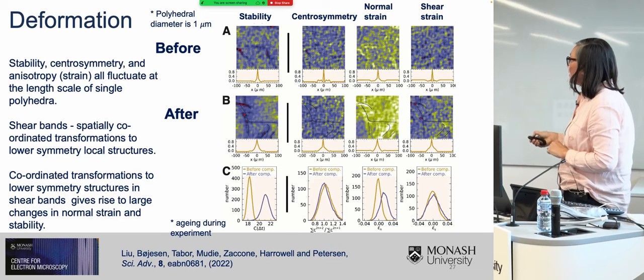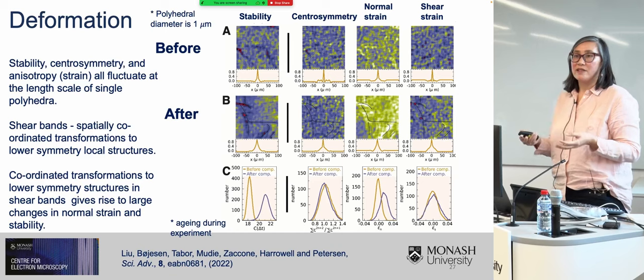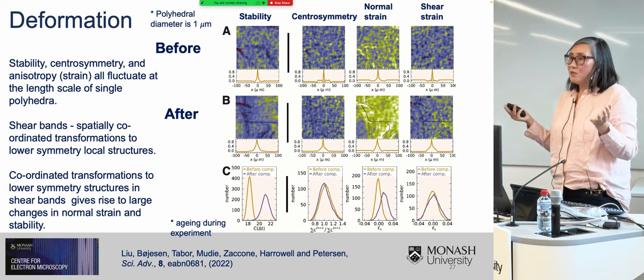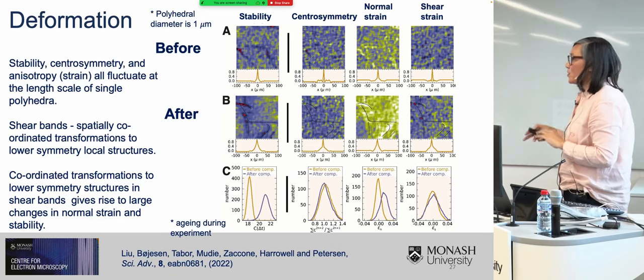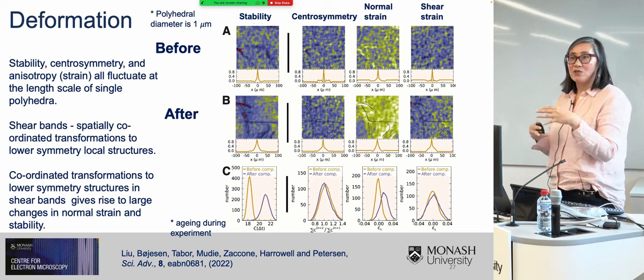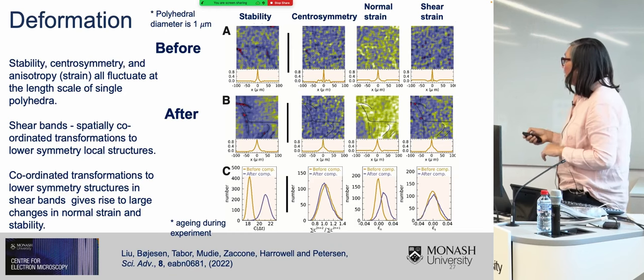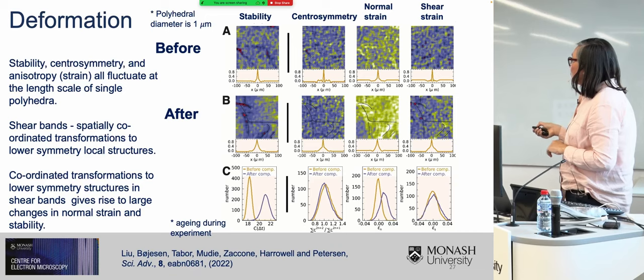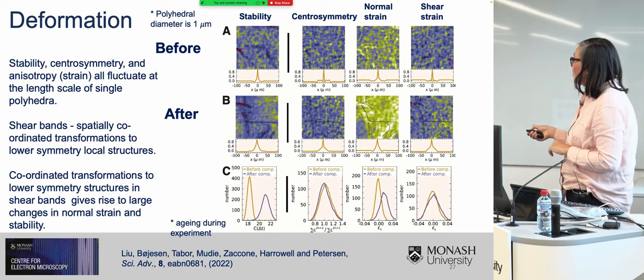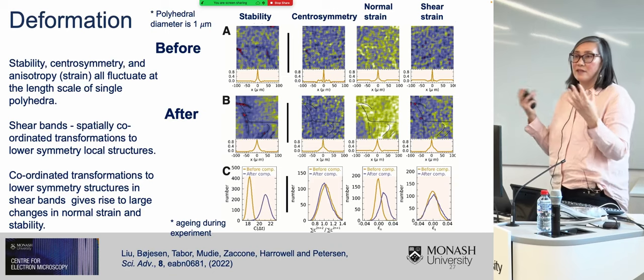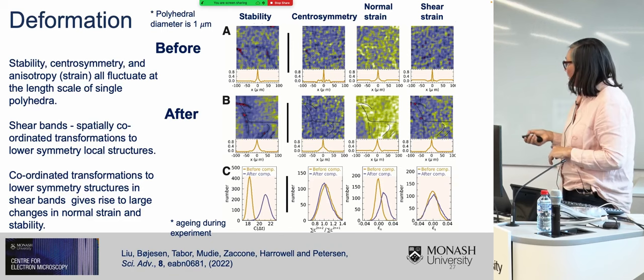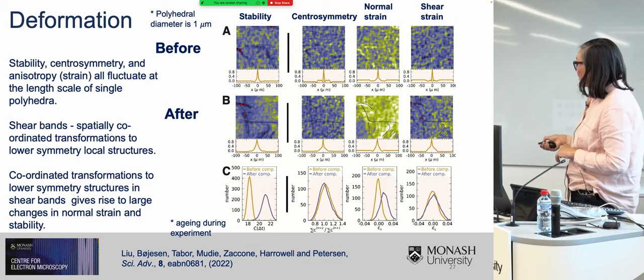And the easiest way to tell where they are is to actually have a look at the local stability, where you can see that in these areas, the local stability has greatly decreased. Now, in a way, perhaps, you can think of this as being like a local transformation back to a phase which is more like the liquid. Now, comparing the correlations between the different maps, you can see that the areas where the stability has gone down also correspond to areas where this local centrosymmetry has been decreased, and also the normal strain has increased enormously. And these trends are also evident from these histograms down here.